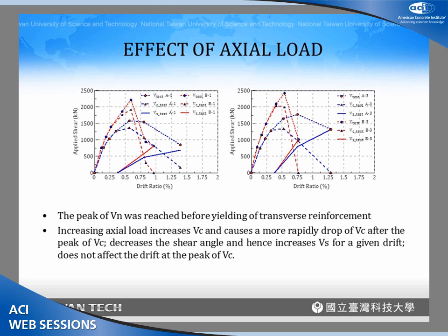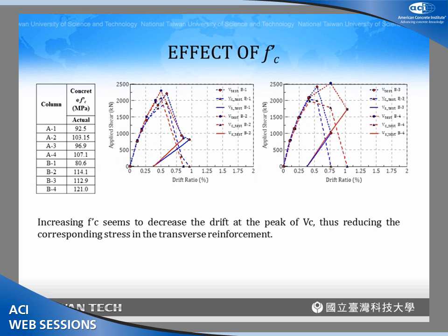This slide also shows you the effect of the axial load. We see that the axial load will increase the Vc, the concrete shear strength, but will cause a more rapid drop of the concrete shear strength after the peak. The increase of the axial load does not change the drift at the peak applied shear. But because the axial load will reduce the cracking angle, the shear strength contribution from the steel reinforcement will be increased.